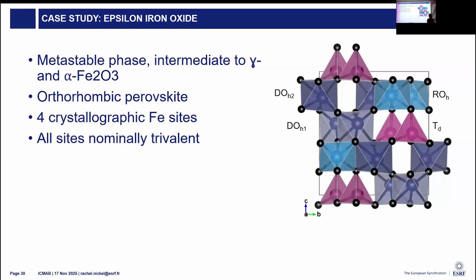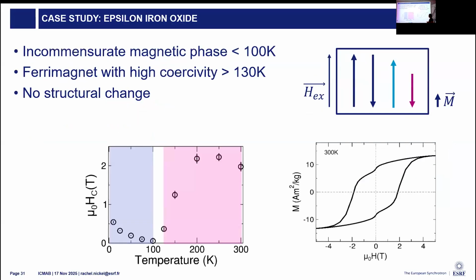All sites are nominally trivalent, which makes it more complicated when it comes to spectroscopy analysis. It has an incommensurate magnetic phase at low temperatures, and at high temperatures, it's a ferrimagnet with high coercivity. So 2 of the sites are distorted, compensated with antiferromagnetic coupling. We have a regular octahedral site and a tetrahedral site, which have an uncompensated magnetic moment that gives the whole material a net moment. We know based off of neutron experiments that there's no structural change that happens between the ferrimagnetic phase and the incommensurate phase.